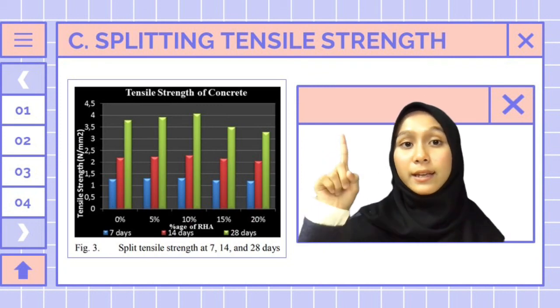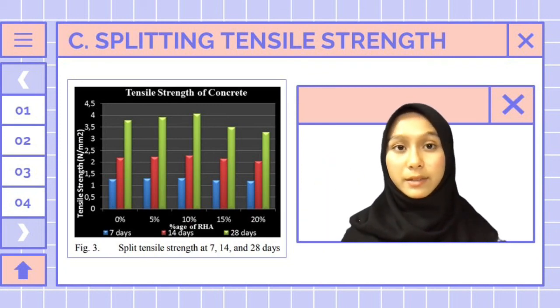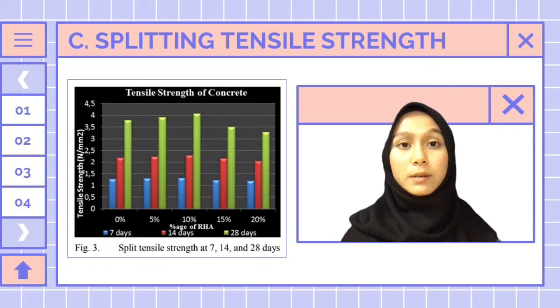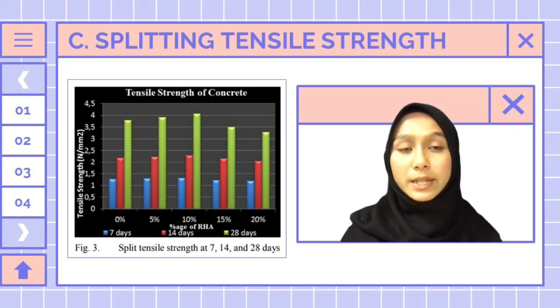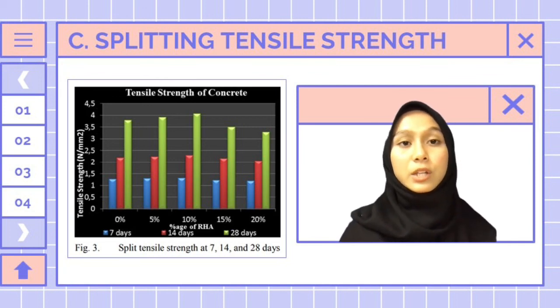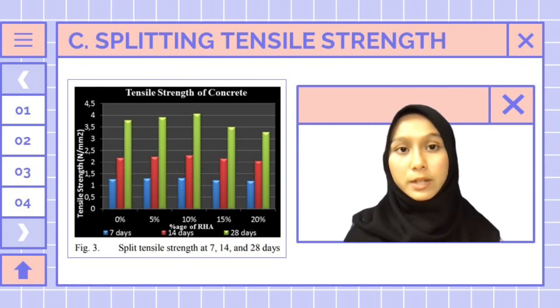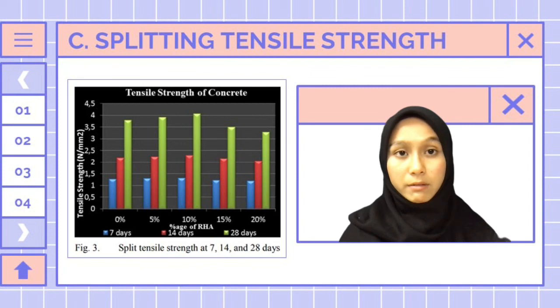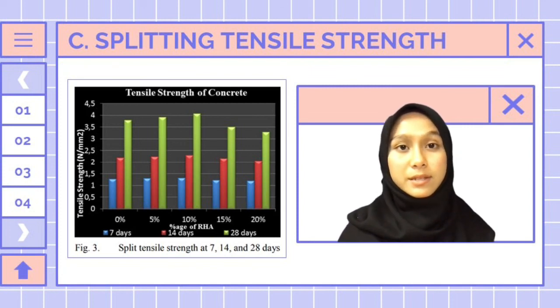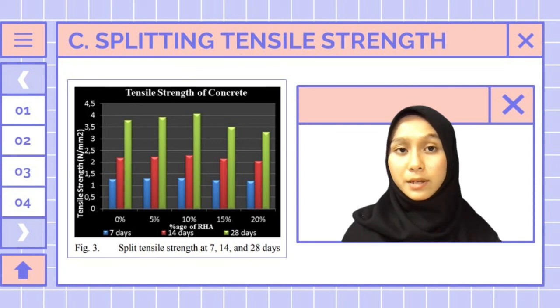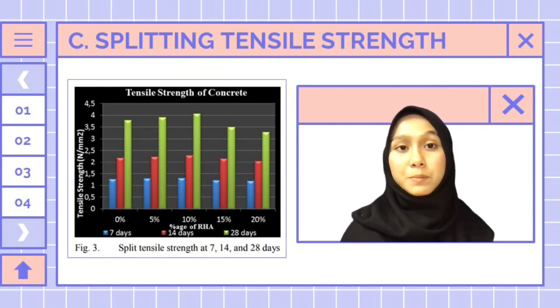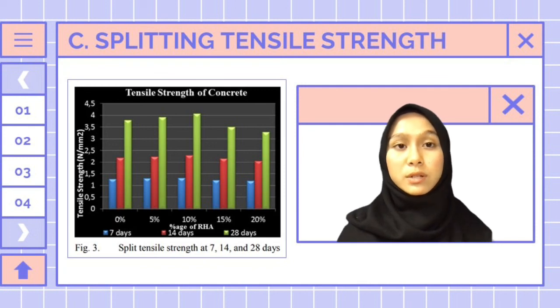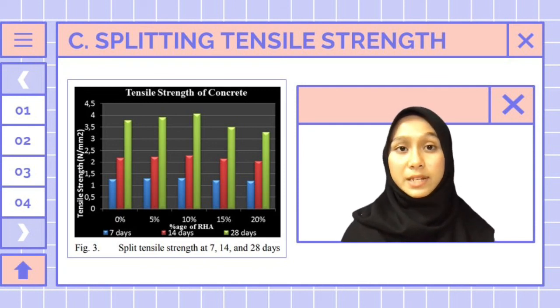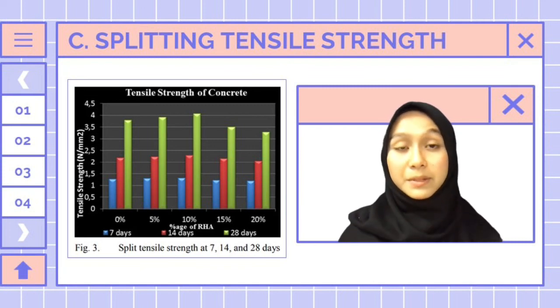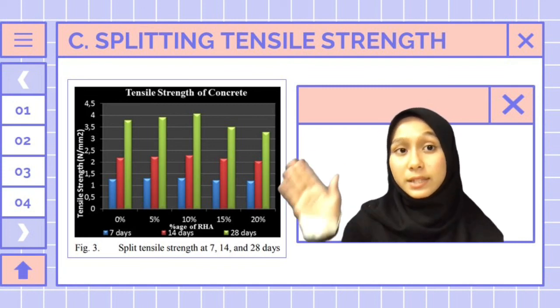Thirdly, Test C, the splitting tensile strength test, was conducted on cylinders of 200 mm times 100 mm with various RHA percentages, cured at 7, 14 and 28 days. Three concrete samples were cast for each proportion, and the average was taken as the final result. The maximum splitting tensile strength of the concrete was noted at the 10% RHA specimen, and the minimum splitting tensile strength of the concrete was recorded at 20%. The cylinders were tested on a UTM. The experimental results are shown in figure 3.